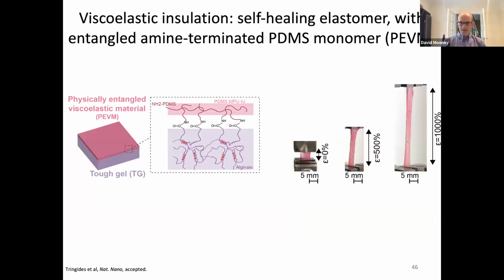Now, to insulate the individual tracks from each other when they're present in an array, we use, again, another viscoelastic material, in this case, one based on PDMS. So we have a self-healing PDMS material that's previously been described. And to get it to interface with our hydrogel, we physically entangle amine-terminated PDMS into this overall PDMS network. And then we form a covalent interaction between the two, very similar to the way we form the covalent interaction between our adhesives and the underlying tissues. We get very good bonding between the two, as you can appreciate that even at 1000% strain, we still have good bonding and no delamination of the PDMS insulator from our underlying hydrogel.